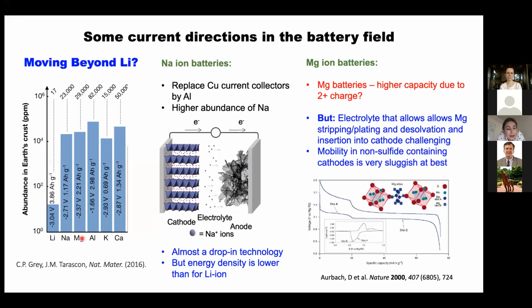Sodium has a potential that's only about 0.3 volts from the lithium potential, and a lot of the chemistry is very similar. Obviously, the higher natural abundance means it's much cheaper, and there are also things that are less obvious, like you can replace the copper current collectors that are in lithium technology on the anode by aluminium or aluminum, depending where you do the chemistry, and that's because sodium doesn't react with the aluminum, unlike the lithium. And so that's another reason for cost reduction.